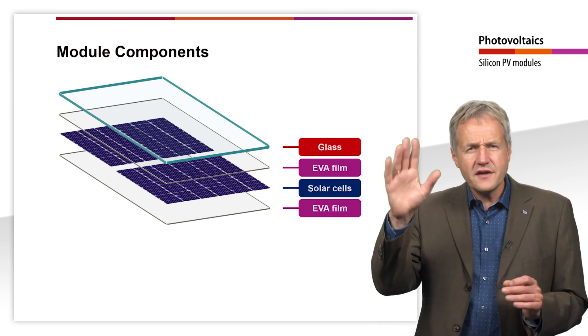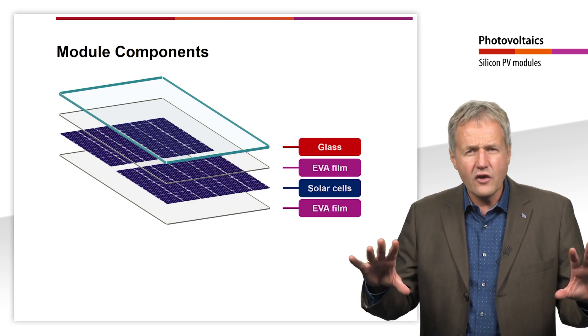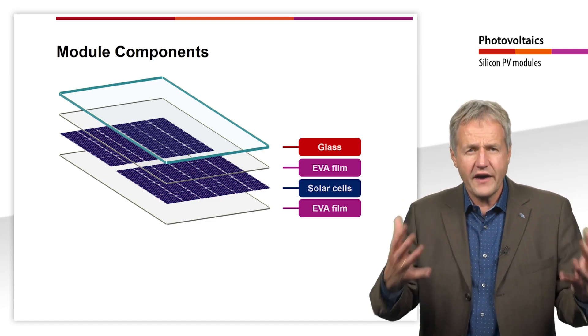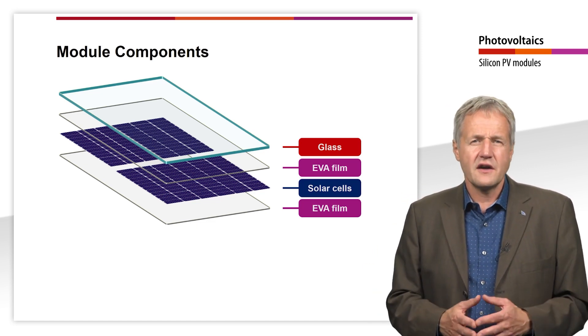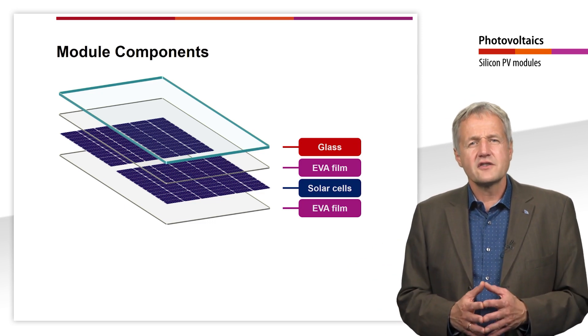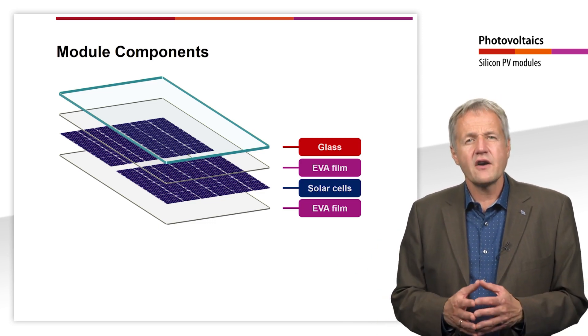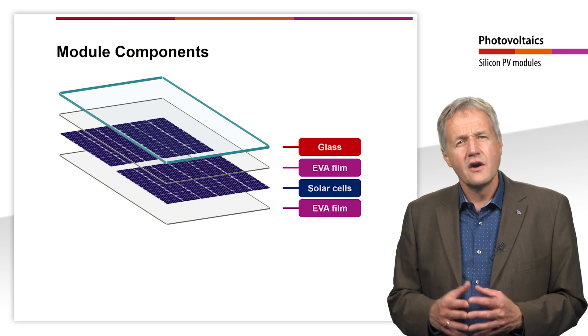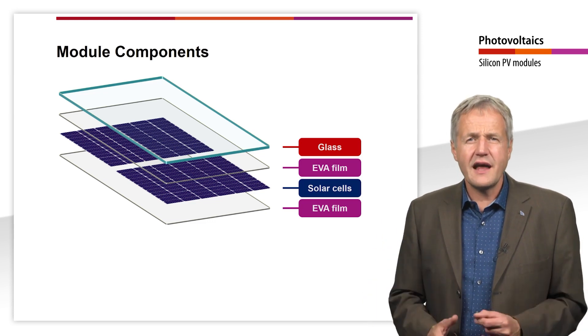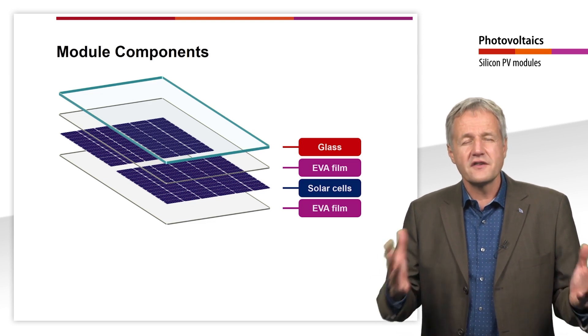Strong reflection occurs at the glass pane, just like at the solar cell. Therefore, the front glass of solar modules is also coated with an anti-reflective layer. Of course, this layer must be optimized for the refractive index of glass, so different materials are used here than on the cell surface. Typical values for the solar transmission of unlaminated solar glass coated with an anti-reflective layer are 94.5%. However, this value increases to 98.5% when the glass is optically coupled with a solar cell, as an optical interface with 4% loss is omitted.